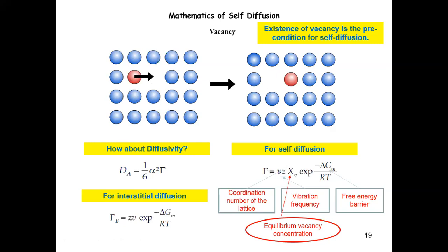And as we analyzed before, we keep the Boltzmann factor. This is the free energy barrier for the hopping. We know that it comes from a different physical consideration, but you still have this term. We have the vibrational frequency. Again, it depends on different types of atoms, but we still have them here. And these two terms together give you the number of available sites, right?